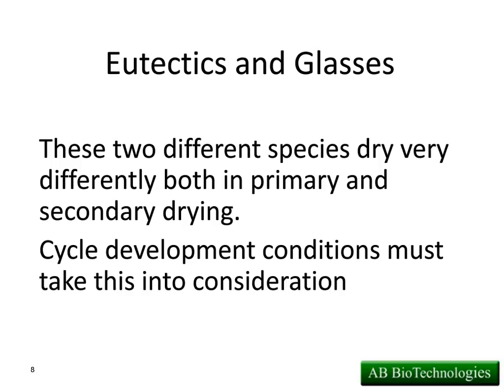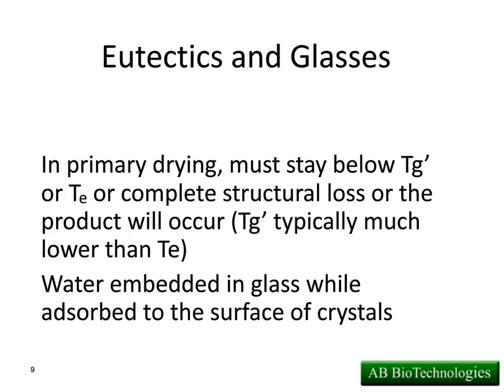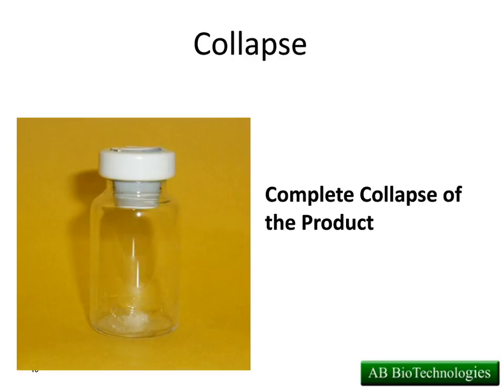Okay, so as I mentioned before, in primary drying, again, we're pulling the ice out of the ice channels. It's extremely important to be below the TG prime glass transition temperature or the TE, the eutectic melting temperature, or we're not going to get a solid product in the vial. It's going to be a puddle of goo in the bottom of the vial. Okay, and this again shows you what you don't want to see.